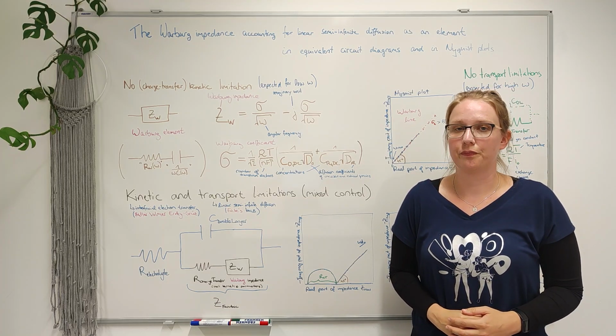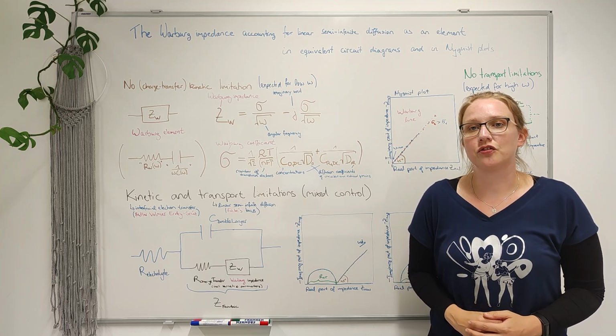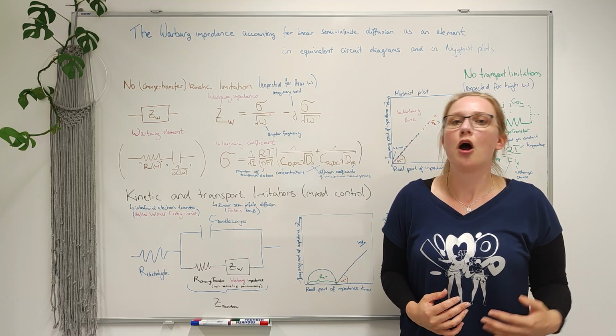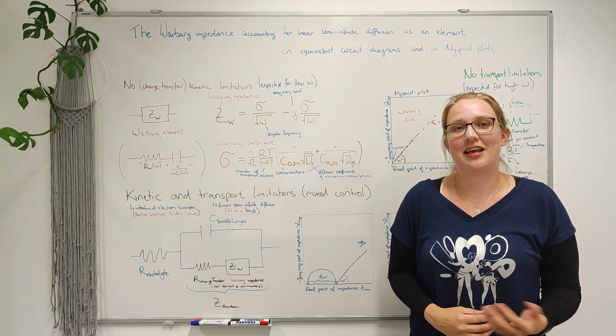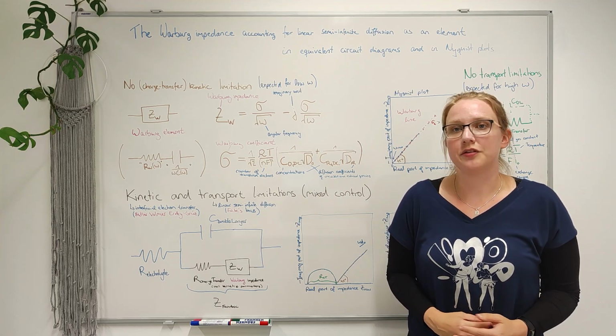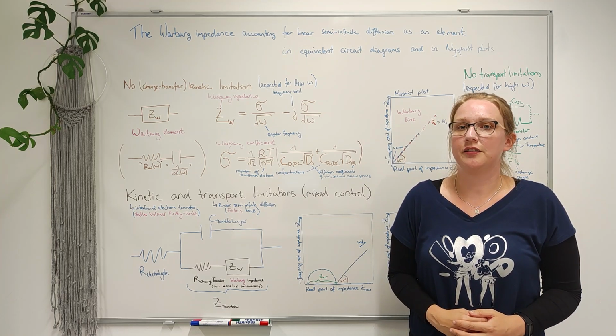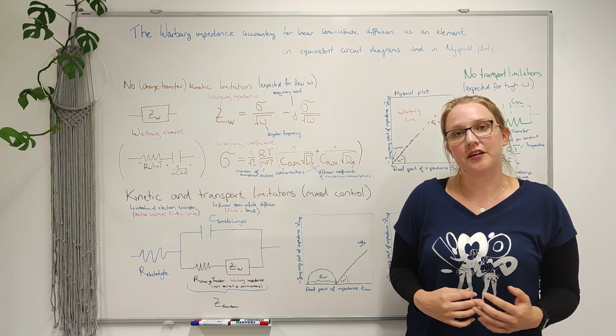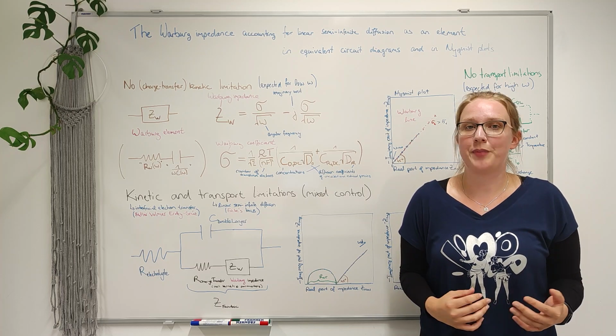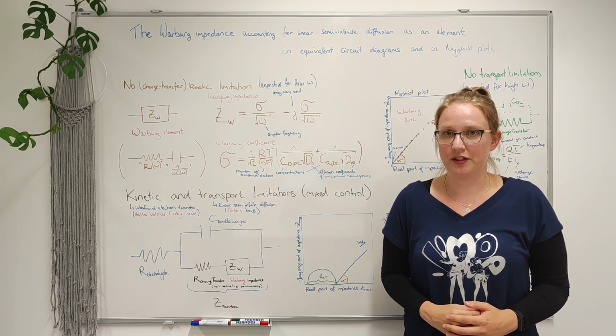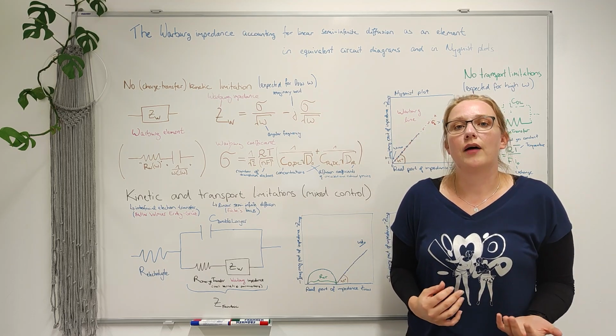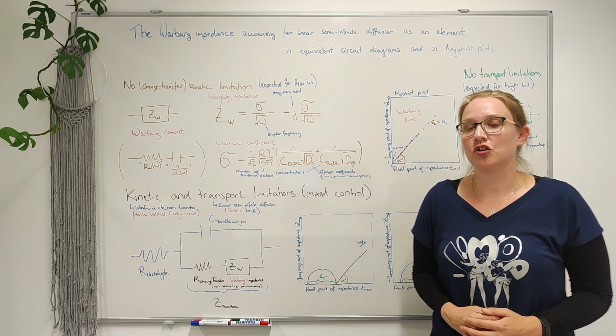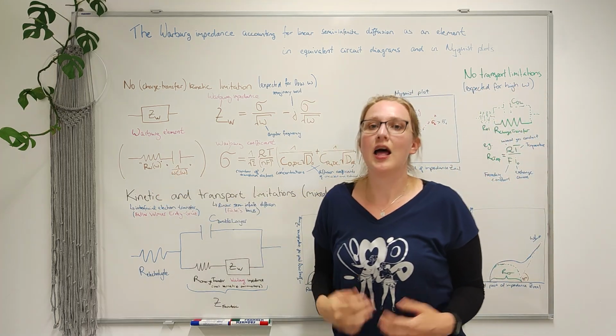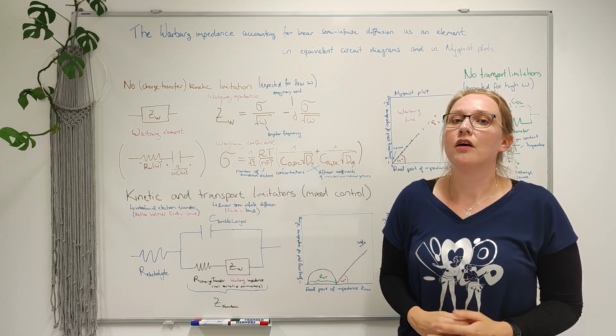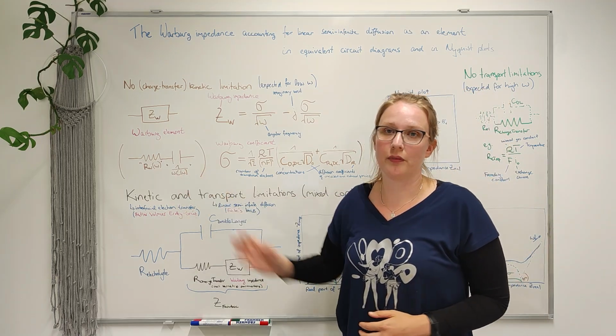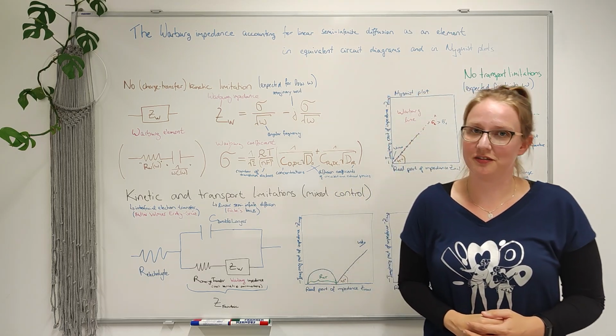semi-infinite diffusion limitations. For an AC perturbation, this impedance describes concentration oscillations at the electrode propagating into the electrolyte as a damped wave. Due to finite diffusion speed, concentration changes are phase-shifted relative to the alternating current through the electrode. How far these concentration deviations from the DC operating point penetrate the electrolyte depends on the frequency of the perturbation. So, the Warburg element can be conceptualized as a series connection of a frequency-dependent resistor and a capacitive reactance, 1 over omega C, with a frequency-dependent capacitance, although such electrical circuit elements do not exist.